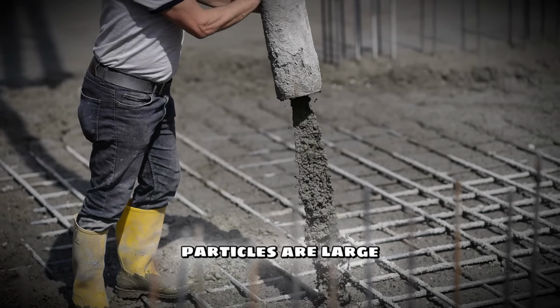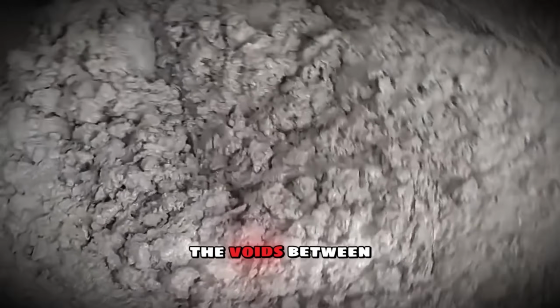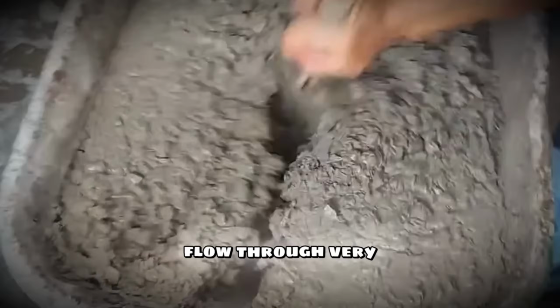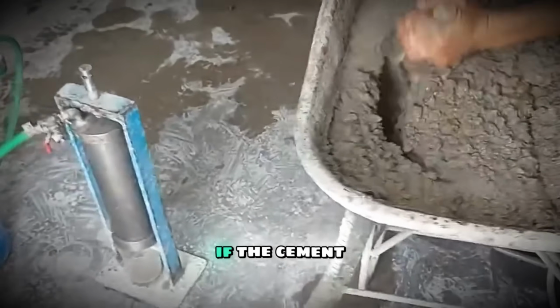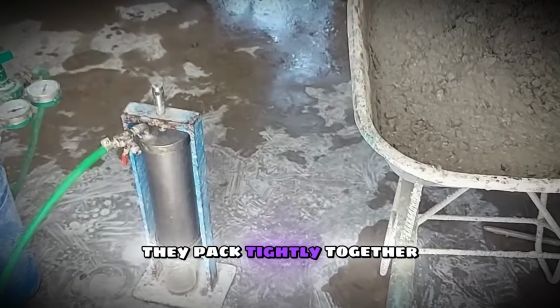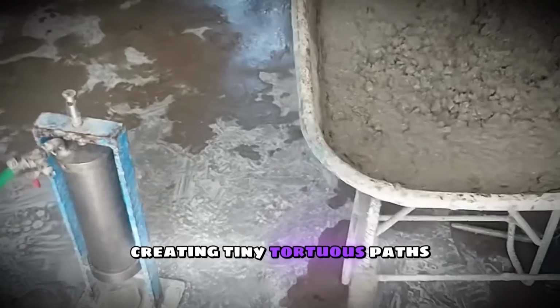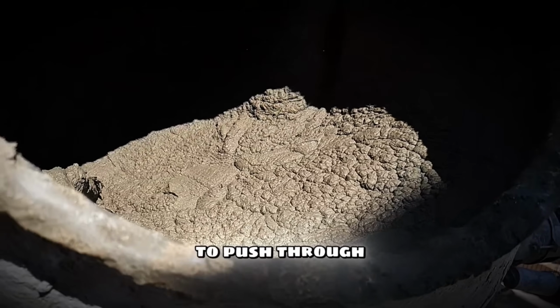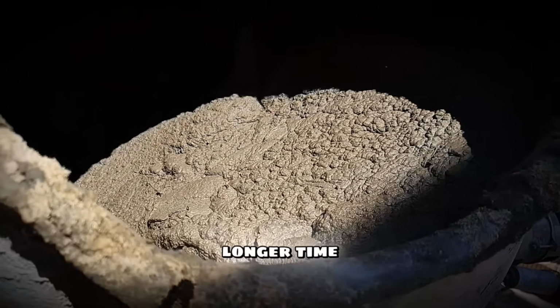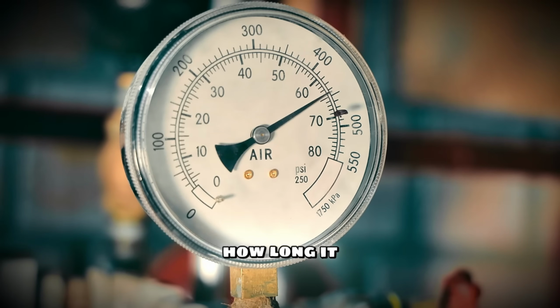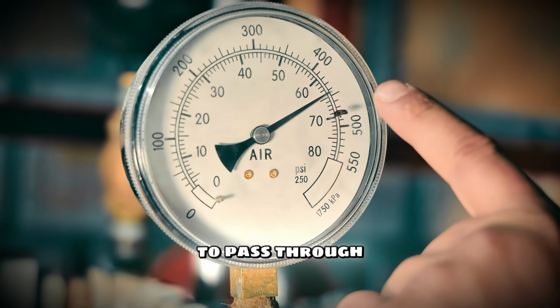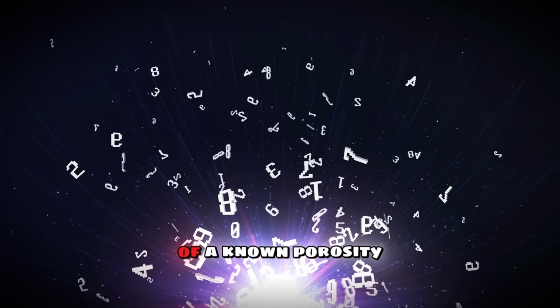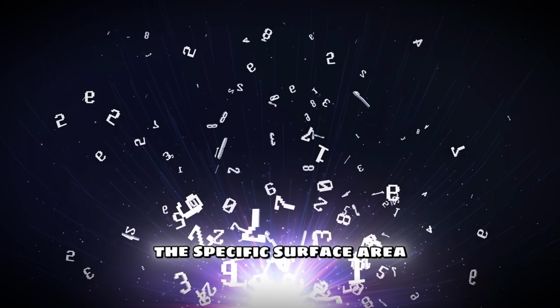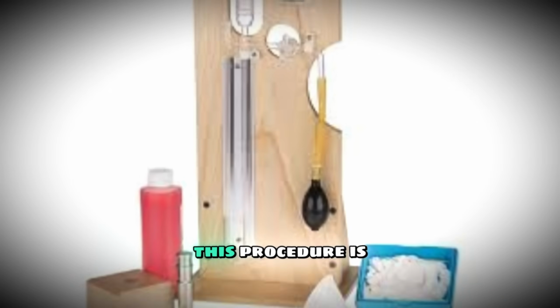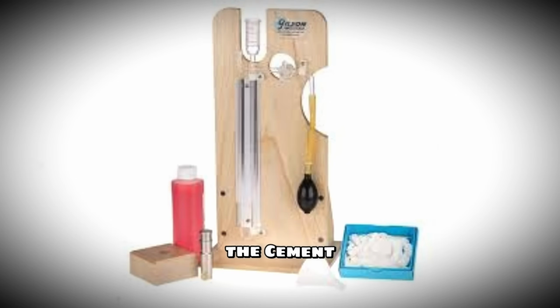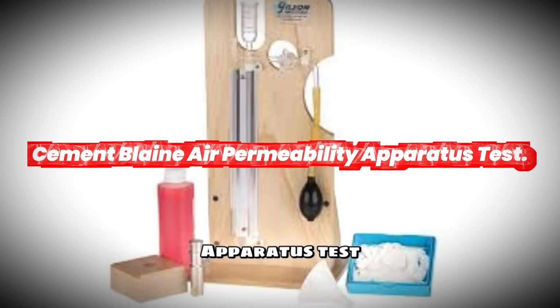If the cement particles are large and coarse, the voids between them are larger, and air will flow through very easily and quickly. If the cement particles are incredibly fine, they pack tightly together, creating tiny, tortuous paths. Air will struggle to push through, taking a much longer time. By measuring exactly how long it takes for a fixed volume of air to pass through a prepared bed of cement of a known porosity, we can calculate the specific surface area. This procedure is universally known as the cement Blaine air permeability apparatus test.